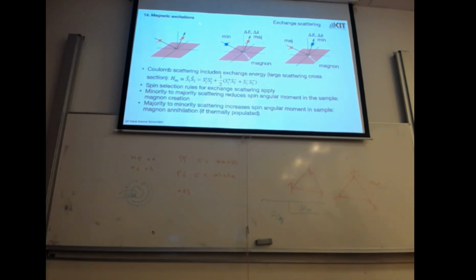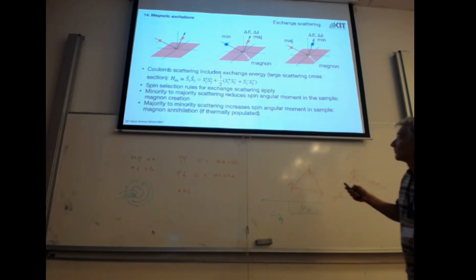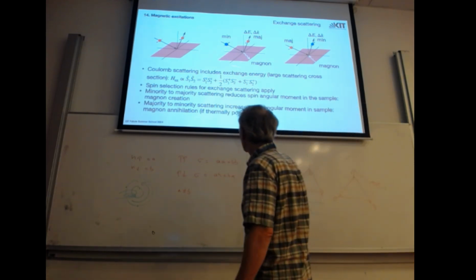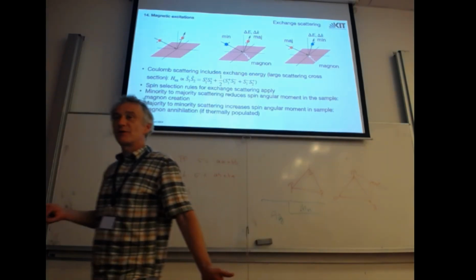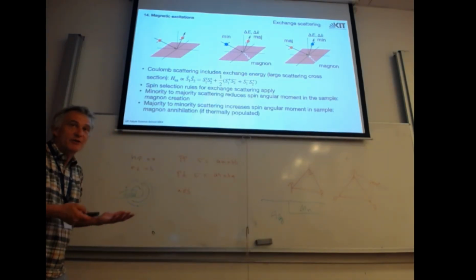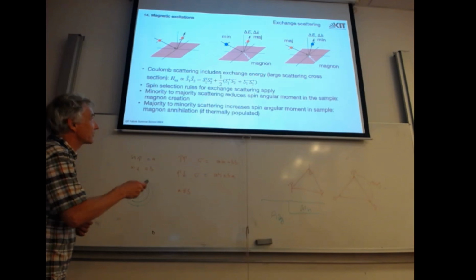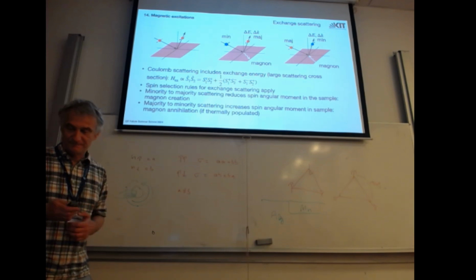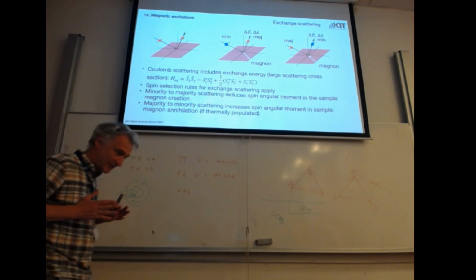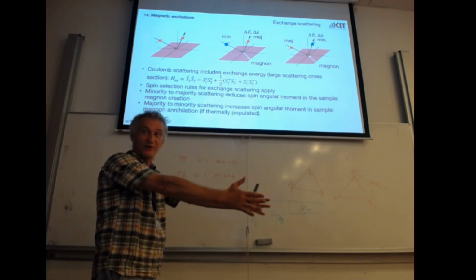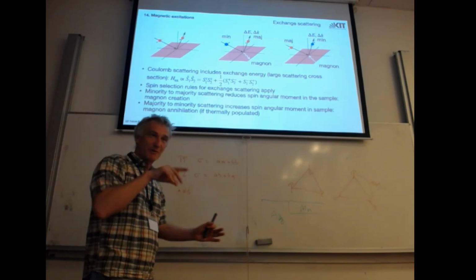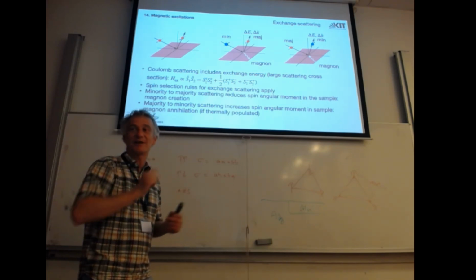What counts for the selection rules is whether you can create magnons or not, if you come with a minority or majority electron. Yes, so minority electron means this spin polarization is opposite to the average spin polarization of the sample. My spins in the sample, in a simple picture, are all pointing in one direction, and if I come with a majority or a minority electron, we get a different result.